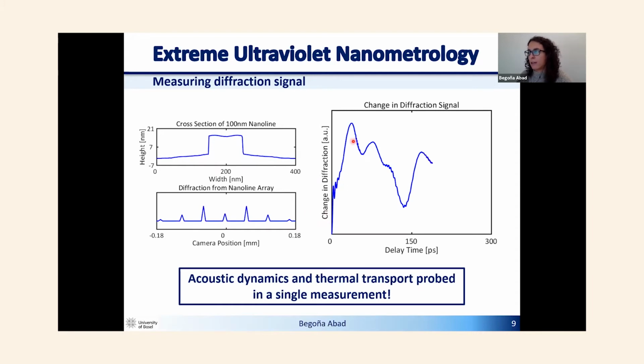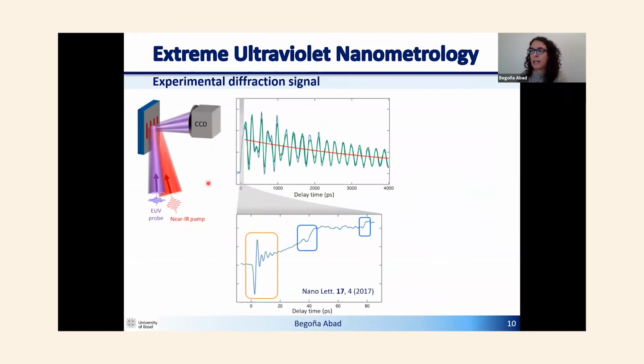As you can see, there are different features that are related with either acoustic dynamics and also with decay, which is the thermal transport given by the substrate. So here we can say that we are able to probe acoustic dynamics and thermal transport in a single measurement. So a little bit more detail.